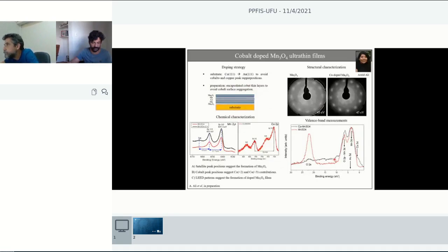As a final example of this series of studies, I tried to make a compilation here going from the bottom to the top. The bottom is where we are looking, since the interface, up to the top of the oxide. I bring you this example here. That's the Mn3O4 films grown in the thesis of Astrid, where we try to change the properties of this oxide, doping this oxide with a small amount of cobalt. So we did a lot of Mn3O4 on gold and copper. The best way to do this doping is on gold, actually, because we can find the spectral signatures better on gold than copper, because of some overlap of the peak positions. But at the end of the day, this result here is Mn3O4 doped, deposited on gold.